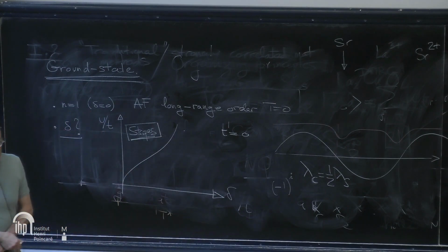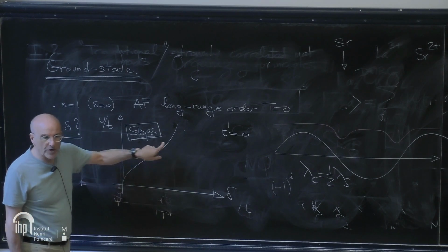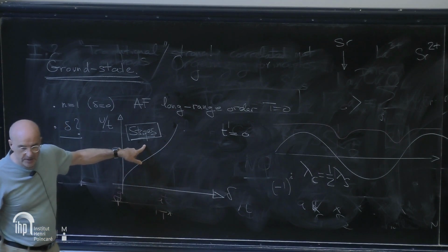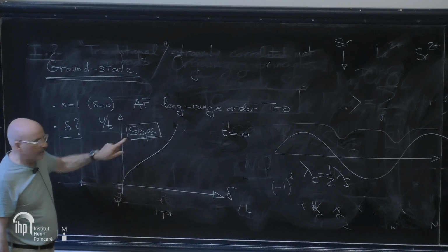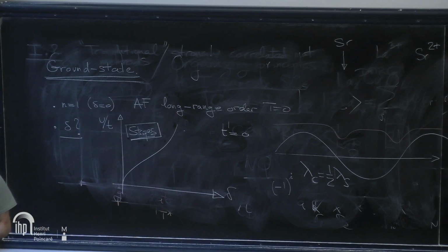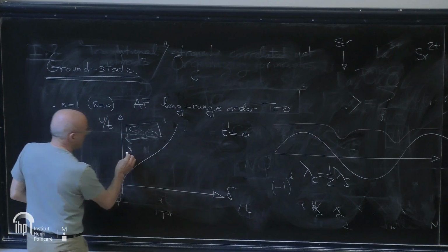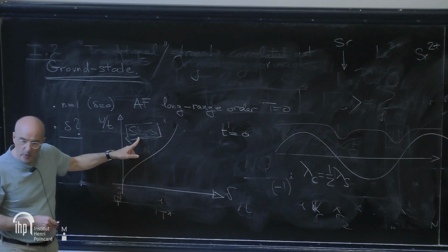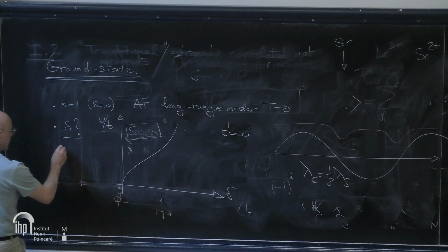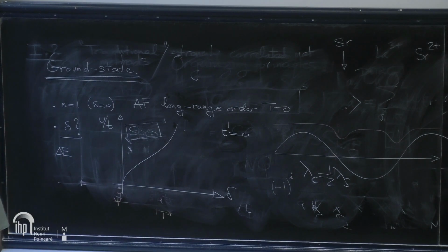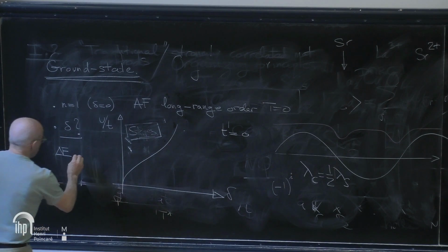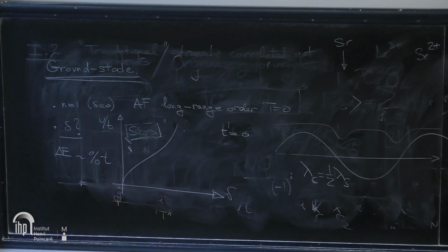So all methods agree that stripes are a very favorable ground state at low doping. The really tough question is whether this wins over, say, superconductivity or not. And this question has been, for most of this phase diagram, answered by highly accurate combinations of DMRG and another method, which is called auxiliary field quantum Monte Carlo, with the answer that at least for most of this phase diagram, when t' is 0, stripes actually win. The tricky thing is that the difference in energy between a stripe state and a superconducting state is very, very small. It is of the order of 1% of the hopping. So this requires very accurate numerics.